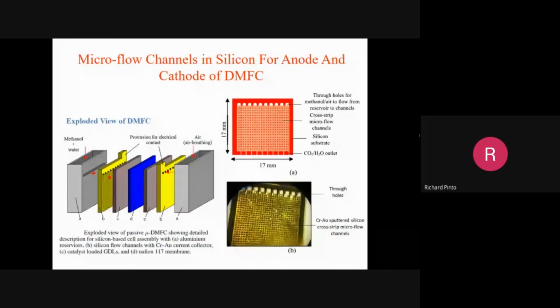C is the catalyst loaded gas diffusion layer. We call it a gas diffusion layer because liquid actually flows to that, and then it breaks into carbon dioxide and H+. This catalyst, as I mentioned, is platinum ruthenium, which breaks methanol into carbon dioxide and H+. Then H+ moves into the Nafion membrane.